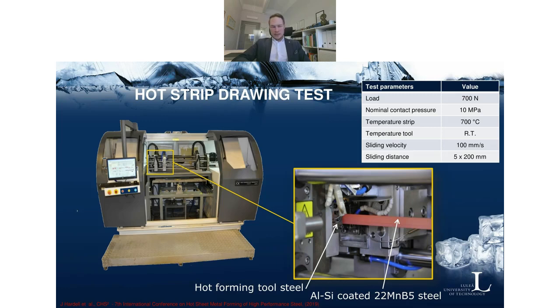The test conditions, you can see them up there. The important part here is two things. One is the temperature. So we ran the test at 700 degrees Celsius. That's the temperature of the strip. And we also ran the test for 5 consecutive runs with new strips for every test. So we did 200 millimeter sliding on one strip, then replaced the strip, but kept the tools the same, and repeated that 5 times.